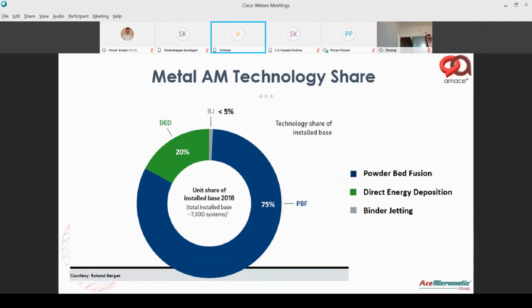So basically the laser melts the powder wherever it's being sprayed on. That way you can print parts of any shape and size as required in this whole technology. And the third one is the new one, which is called binder jetting, which I explained some time back. It's also an interesting field where you have a binder, which is more like a glue, sprayed selectively in areas where you'd want the bonding to happen. And then the next layer of powder is laid, and again the binder, which is the glue, is sprayed.